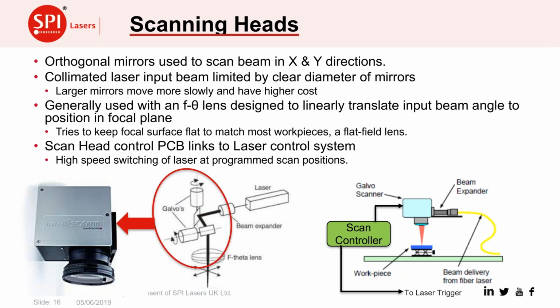One way around this is to use a scanning head, where you have orthogonal mirrors in the X and Y direction, just shown in that kind of red ring there. These scan the beam in X and Y. You take the beam out of the laser fiber, collimate it, and send it onto the mirrors, and that scans over the F theta lens, which translates that angular movement into an X and Y on your workpiece. The F theta lenses are generally specific lenses designed to give you a reasonably sized flat field so that you can keep the beam in focus over the workpiece of maybe a few hundred millimeters, depending on the application. And the scan controller comes with a scan head, which is linked to the head to move the mirrors, and at the same time provides a trigger out to the laser, to turn the laser on at the right pre-programmed positions.